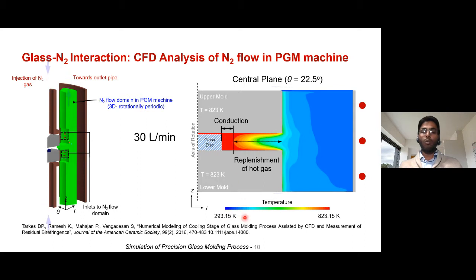I'm showing the contour plots for a temperature between 20 degrees centigrade to, let's say, maybe 550 degrees centigrade. So here you can see that there is gas conduction actually happening, and as you move slightly away from this region, there is a gas flow happening. So there is gas conduction happening till this region, and after that there is a gas flow, and then the hot gases are being evacuated out. So this is the mechanism through which the heat transfer is taking place.